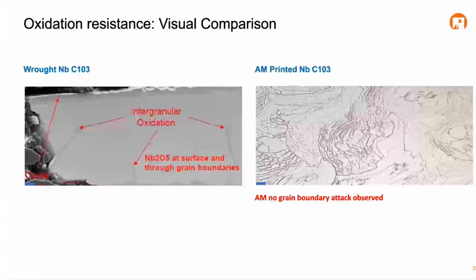When we look at the AM material, we have these tortuous grain boundaries that don't allow the oxygen to penetrate, and we also get a mechanical interlocking effect of the grains themselves. We're able to see that we have better oxidation resistance.